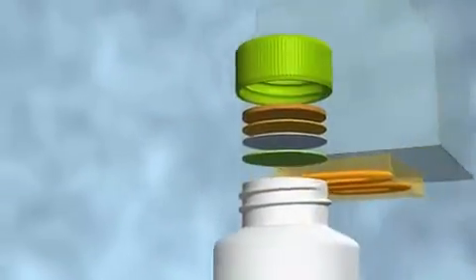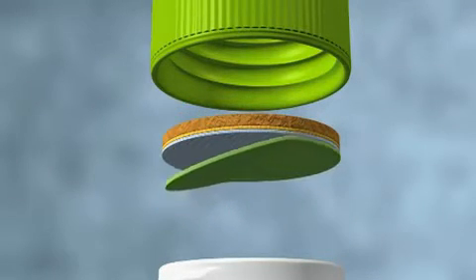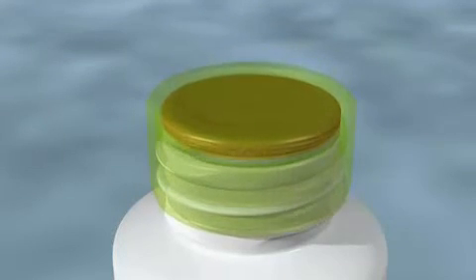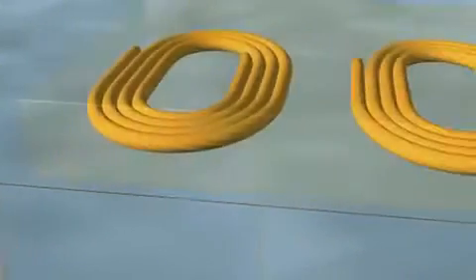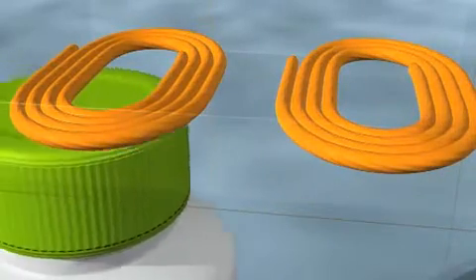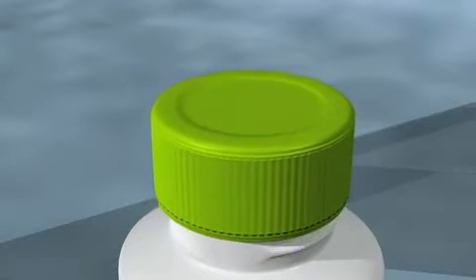The foil seal is made up of laminated products, of which there are hundreds of different types depending on the application. The membrane is coated on one side with a sealing resin, adhesive or polymer to suit the application. The membrane is placed in the closure or cap and then applied to the neck of the bottle or container to be sealed. Our expertise also takes into account other important production factors such as the closure application. As the container moves under this part of the machine, an electrical current is applied to the induction coil that radiates a magnetic field, which heats the foil to an exact temperature to melt the resin, adhesive or polymer to the neck of the container, which forms a strong yet flexible hermetic seal.